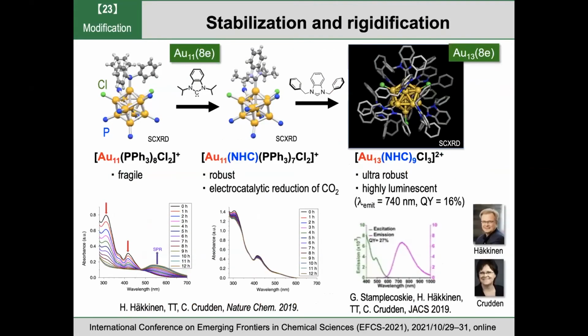Au11 clusters are another famous superatom, which are protected by phosphine, but they are very unstable in solution. But if we replace one of the phosphines with a carbene, the stability can be enhanced dramatically. So replacement of a single ligand can enhance the stability dramatically. And if we fully replace the ligands with carbene, the stability is enhanced much more, and the photoluminescence quantum yield can be enhanced dramatically, up to 16%. So carbene is a promising ligand to stabilize the clusters.